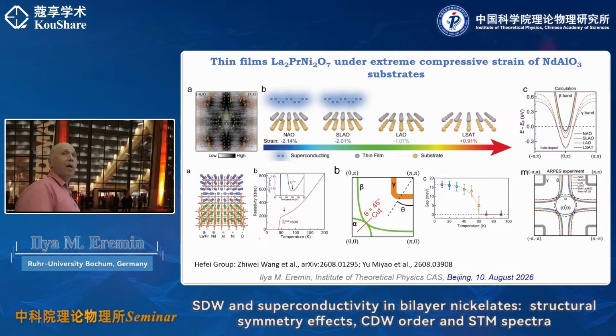So they provided this evidence, and they also measured the fermiology of the system and the size of the gap, which is consistent with all the other values that have been extracted. And even more, they saw how the fermiology changes as a function of the substrate. So we see that even now, two years after the initial discovery, there are still exciting findings going on. They could study how the fermiology changes as a function of the substrate, which is very, very nice.